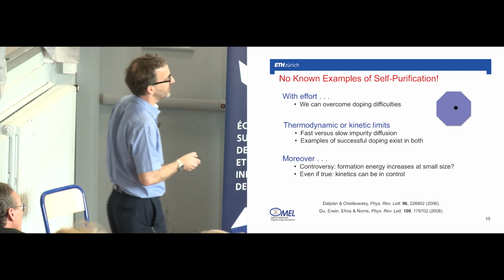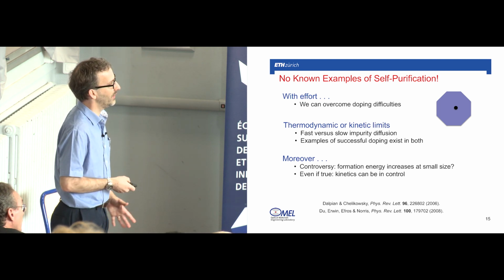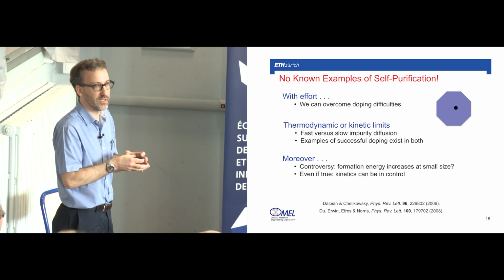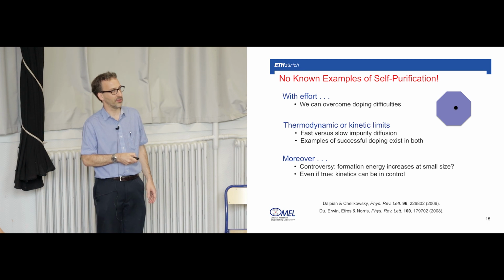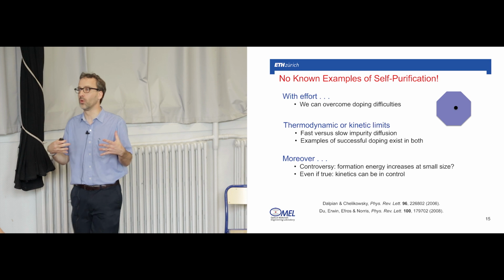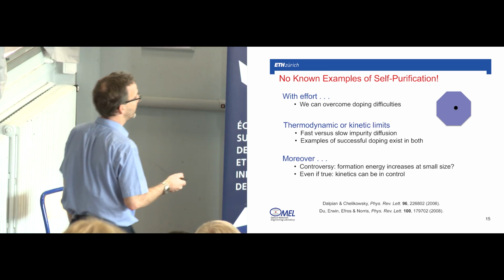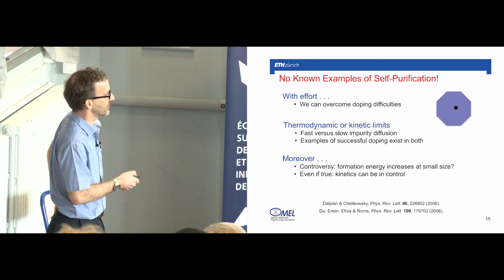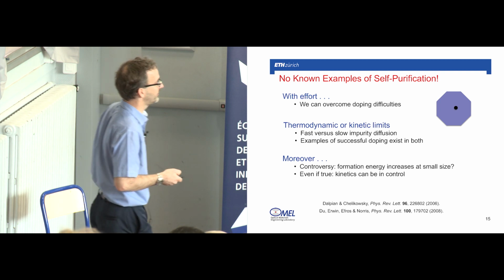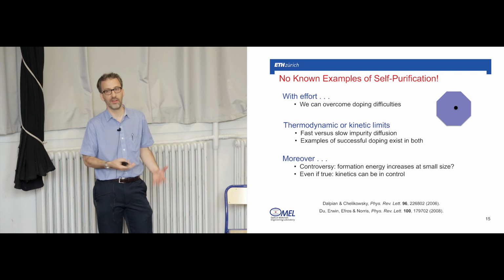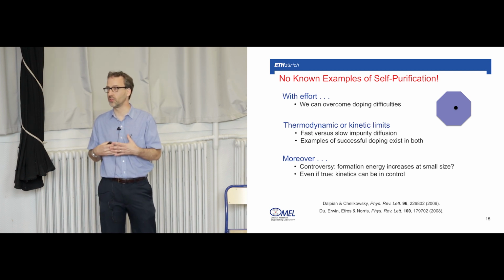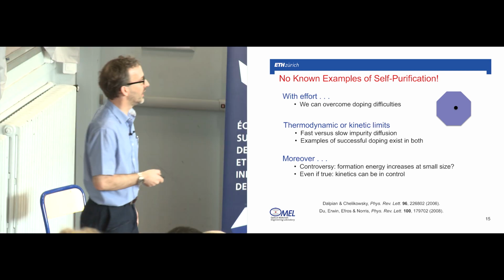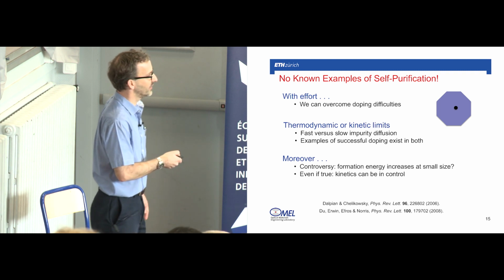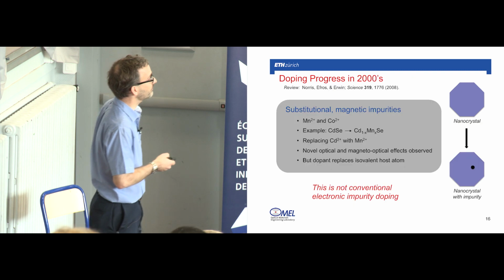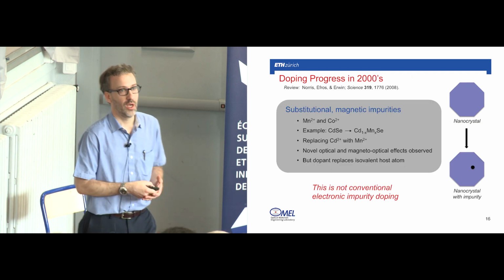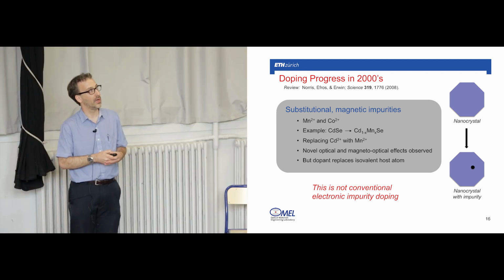And moreover, there's been a controversy over this report that I mentioned, that the defect formation energy of the impurity increases with decreasing size. That was reported here by Jim Chelikowski's group. And Steve Erwin, who I was collaborating with, did a huge amount of work to try to reproduce those calculations using all kinds of different codes, and they could never get it to increase with decreasing size. I'm not an expert in that, but it's still very controversial. Even if it were true, we have to keep in mind that in examples like the manganese examples, nanocrystals grown at relatively low temperature, a few hundred degrees, kinetics is in control anyway. So diffusion is not that active, and it would be hard to imagine that this self-purification idea would be active.